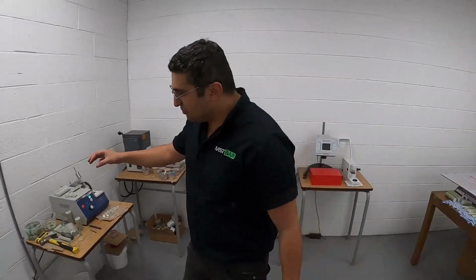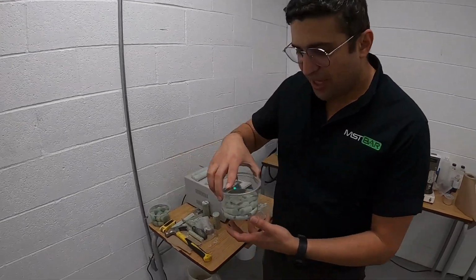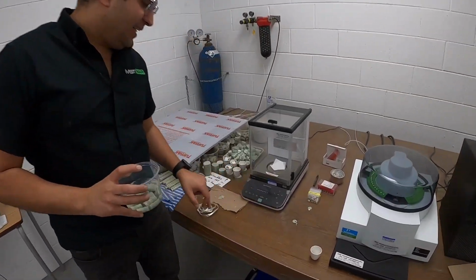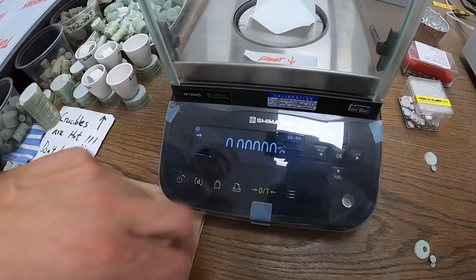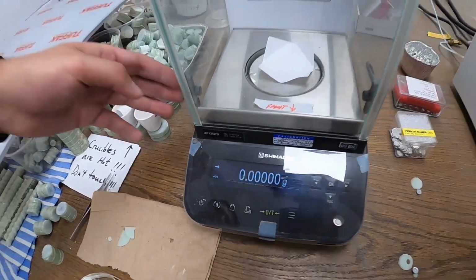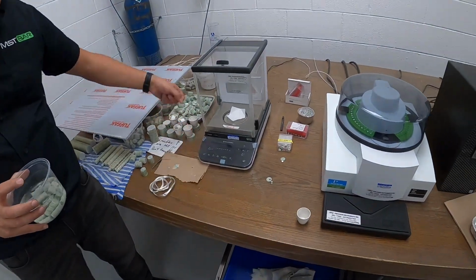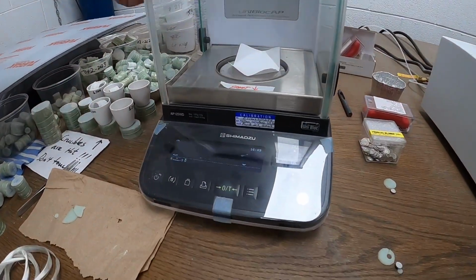Some of the other crazy tests we do, Matt, is we put a piece of rebar in water and we weigh these bars every day to see how much moisture they're absorbing. And look at the scale, Matt. The scale that we test this with is 0.00000 grams. If you look at that, Matt, it can measure air.